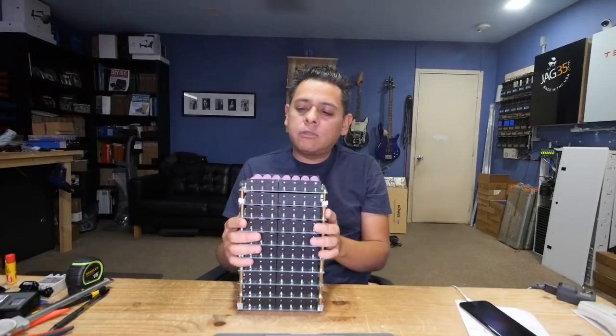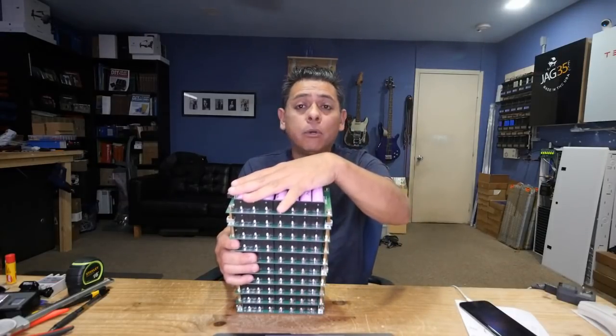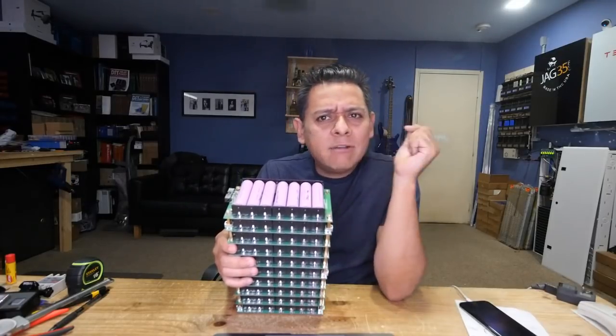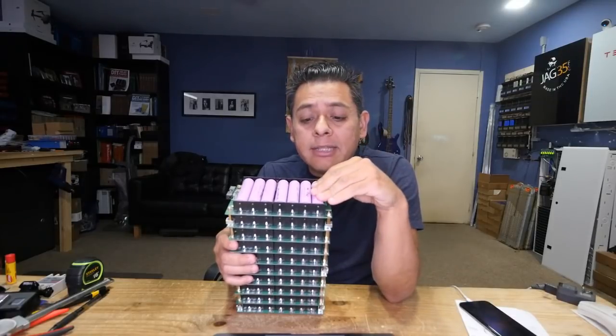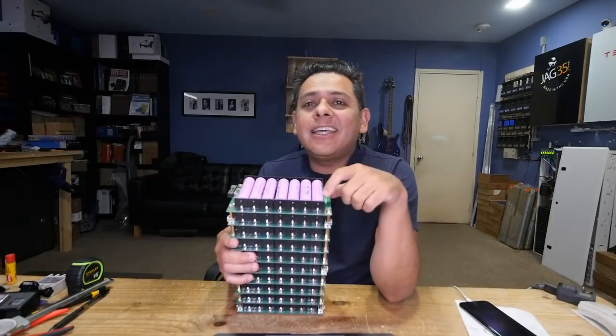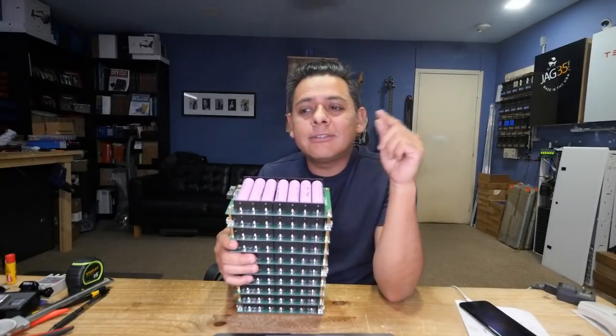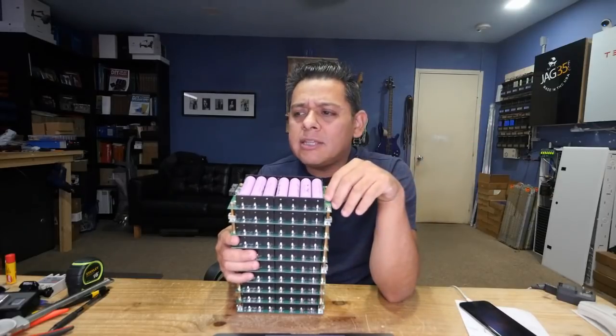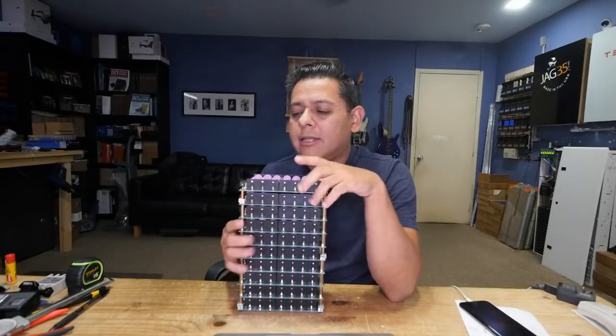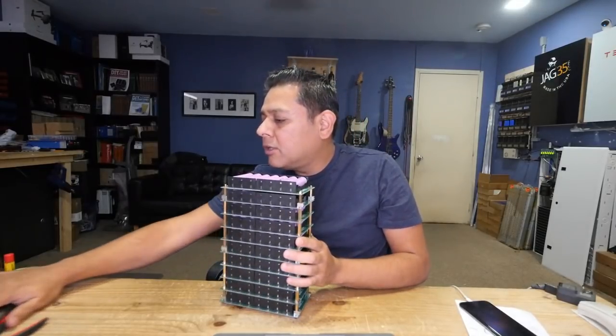Yeah, these work for 18650s. These are cheap Chinese batteries that I imported to the United States. We did quite a bit of them, I think like 30,000 of these cells or something like that, and then we sold them, and then we did cycle testing, and these batteries did almost 1,000 cycles, right? Even though they're rated at 300 cycles. I don't remember if we went easy on them, I think they were full depth cycles, but we kind of did what would be the life on a power wall, on a storage setup, right?